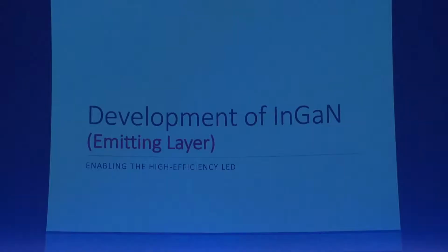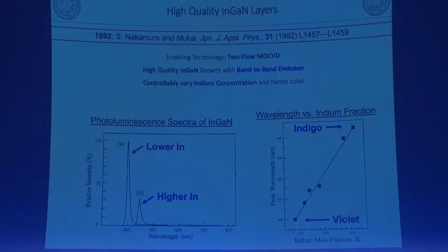And the next is the emitting layer, indium gallium nitride. This is also very important. This layer emits blue light, green light, all kinds of color. Several groups tried to grow this material. Nobody could get high quality material which shows blue emission, green emission at room temperature. Nobody. But in our case, using two-flow MOCVD, we observed the first strong blue and violet emission.